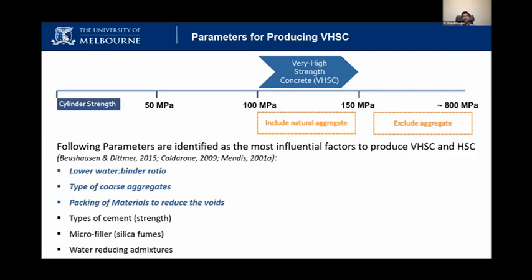Another factor is the packing of material to reduce the voids. As I mentioned, water creates voids and makes the concrete porous. Also, if the materials are not packed properly or settled within the concrete mix, it can create voids in between. So the packing is very important. We usually use a packing algorithm to create the best composition to get a dense mix. For that, we analyze the particle size distribution curves and run the algorithm, which then gives the best percentages between the materials to get the best packing density.